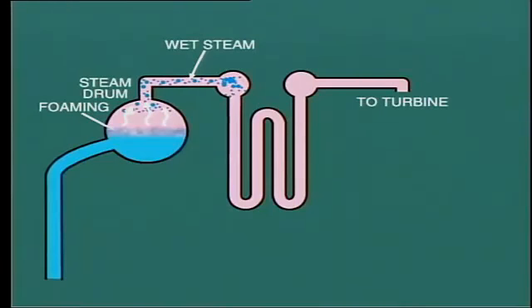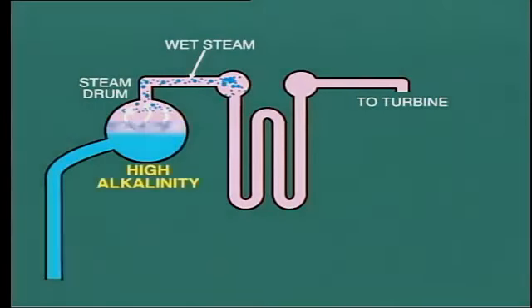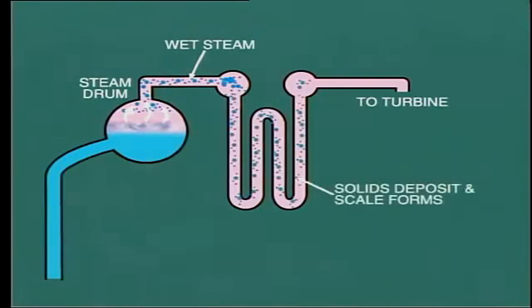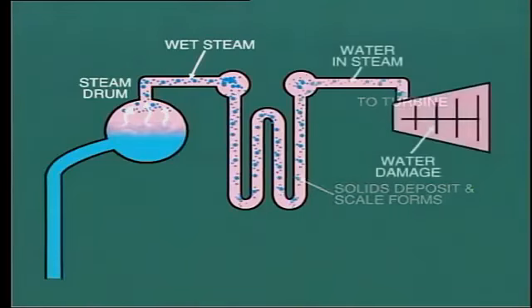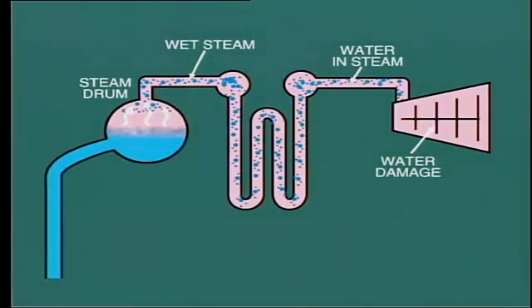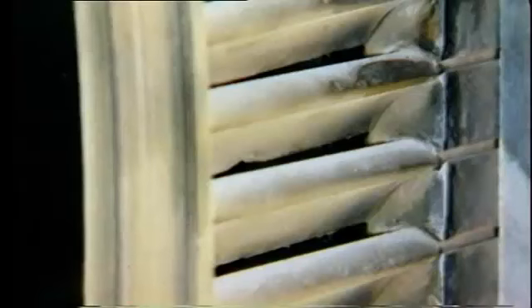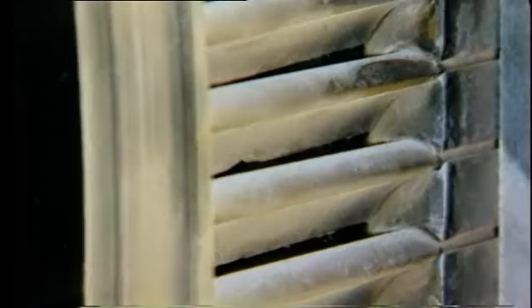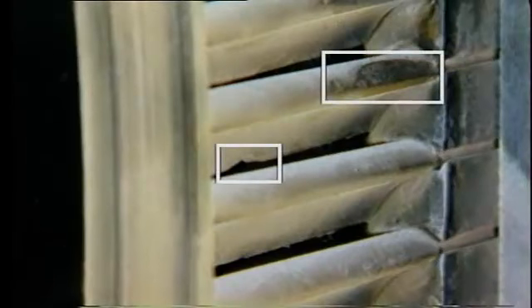Carryover may also be caused by fluctuating water level in the drum or a persistent high water level. High alkalinity in the boiler water may also contribute to carryover. The result is that water is carrying on through the superheater, possibly depositing solids and forming scale on the inside of the superheater tubes. The water droplets may also pass along with the steam into the turbine. Here, the water and solids material can cause considerable damage when striking the rapidly rotating turbine blades.